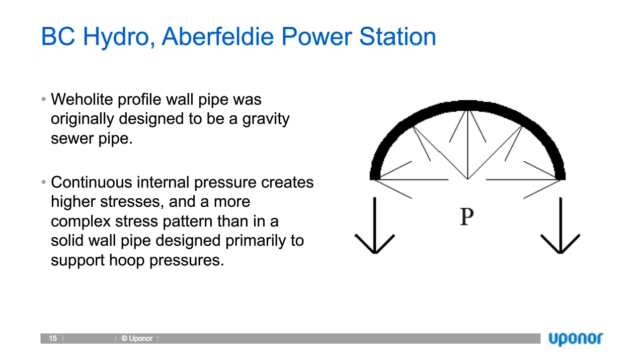For elastic pipes, and most of these other materials that Grant spoke about are elastic materials, steel and concrete, the pressure rating for the material is fixed, is constant, regardless of the duration of the load. Essentially what that means is on a stress-strain curve, you're working in the linear portion of the stress-strain curve. Stress it, get a very small amount of lengthening, you remove the stress, and it returns to the original position. For hydropower applications and for irrigation applications, the pressure hydraulic grade line is typically well above the obvert of the pipe, so it's under constant pressure.